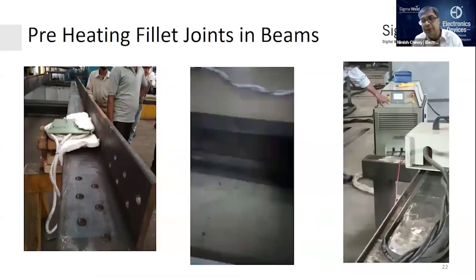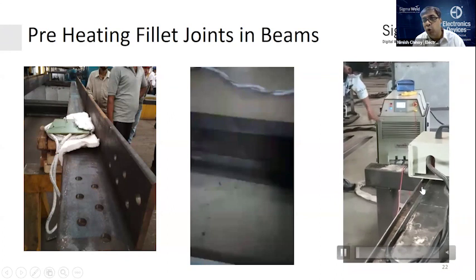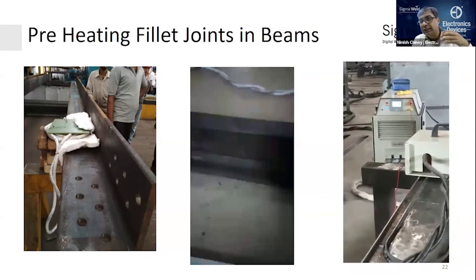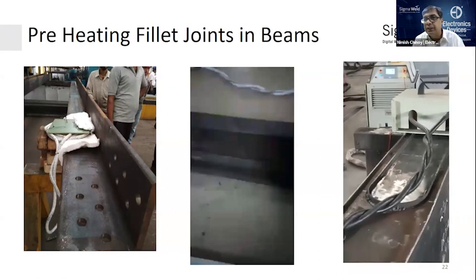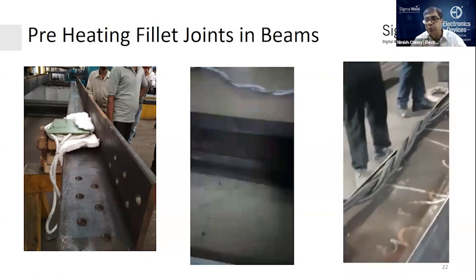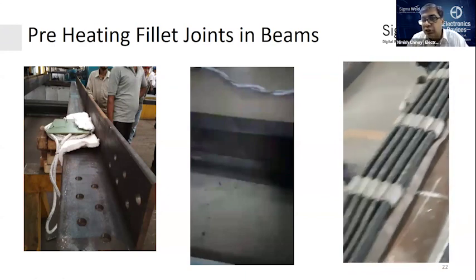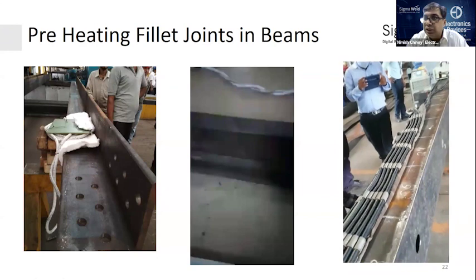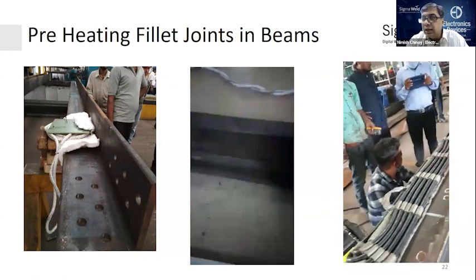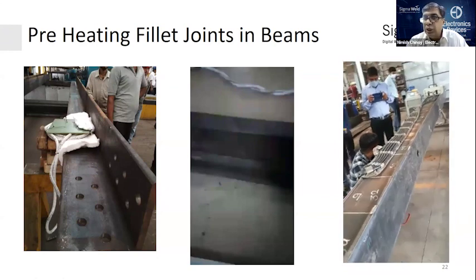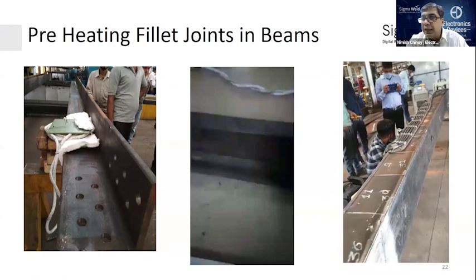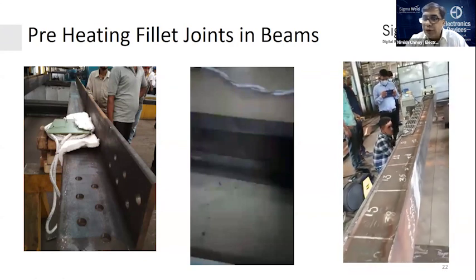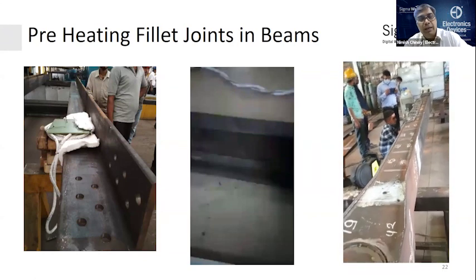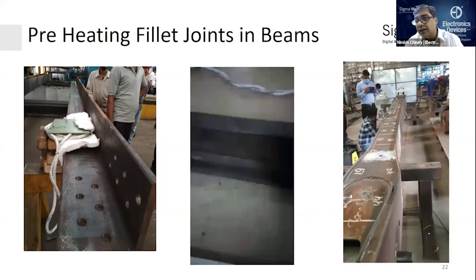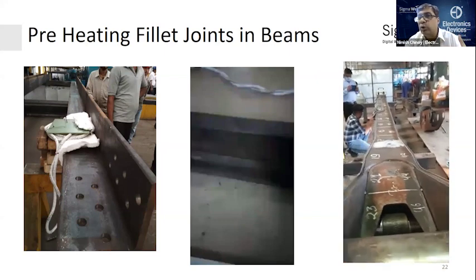These are different examples. This is a good one where you can see preheating of a boom in the construction. You use these material handling equipments like JCB and all. They have a large boom. If the boom is not stress relieved, preheated and then stress relieved, there are good chances that under load conditions it will fail. So it needs to be preheated. Typically it was preheated with gas, but it would take a lot of time and the operator needed to be very skillful and consistent, because if he did not heat, there was no way to know it was not done.